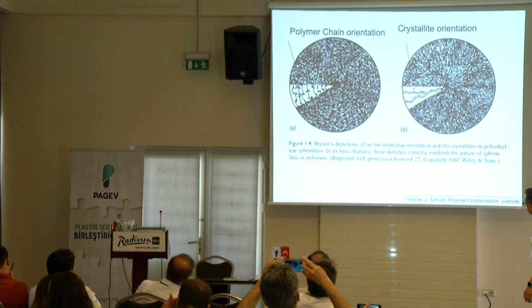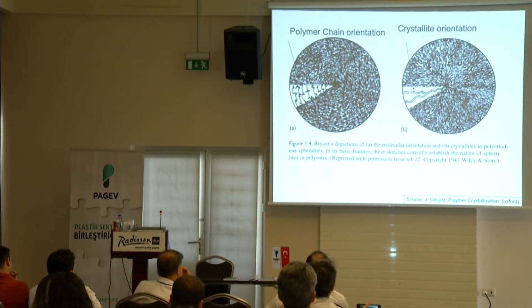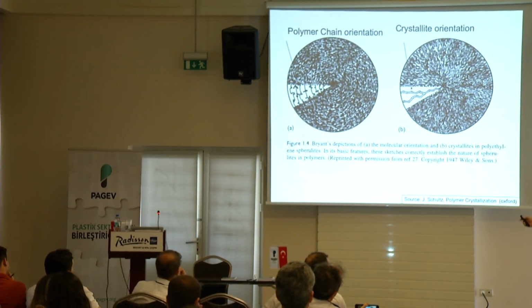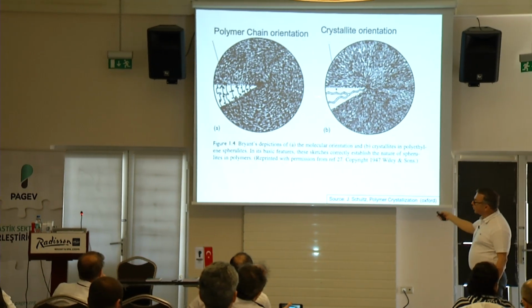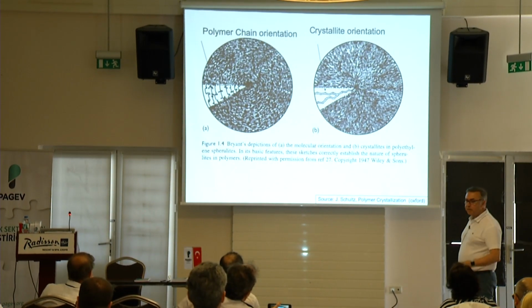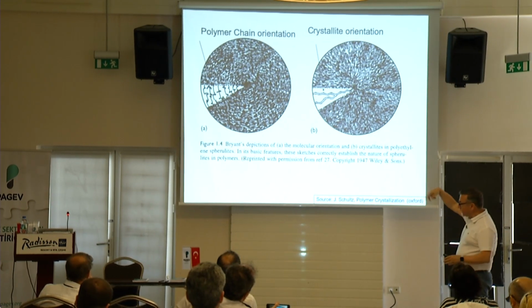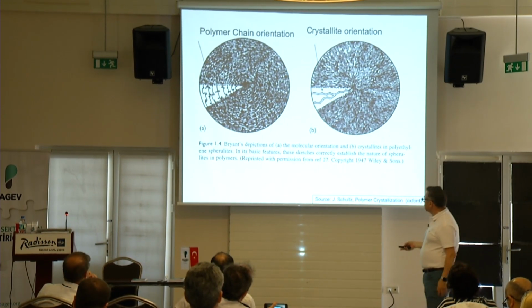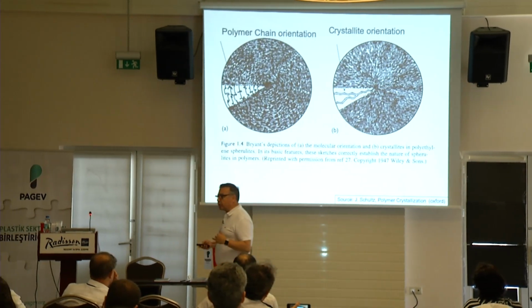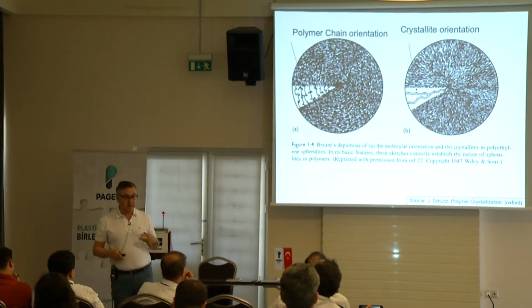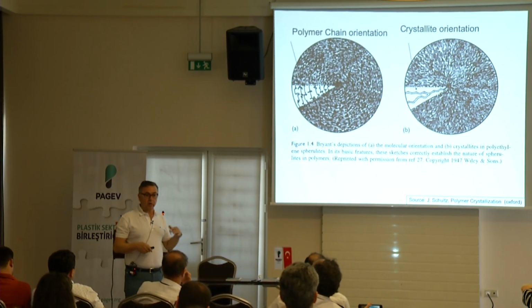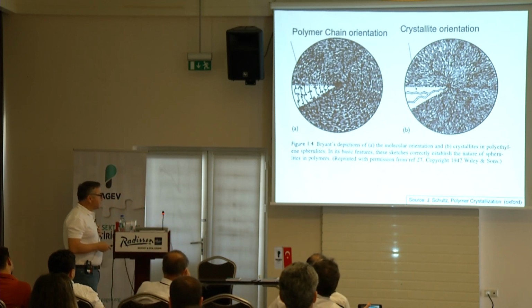Remember, the lamella is growing radially, right? Mostly radially, some splaying. But within the lamella, polymer chains are sideways. So when you look at the morphology, the material's polymer chains are actually tangential to the growth direction. So 90 degrees, because of the fact that they're all folding and then just simply going up and down, up and down, up and down. So this is an important thing to keep in mind, especially if you're doing post-processing with this material. If you're doing cold rolling, for example. These details become important in the material's morphology behavior.